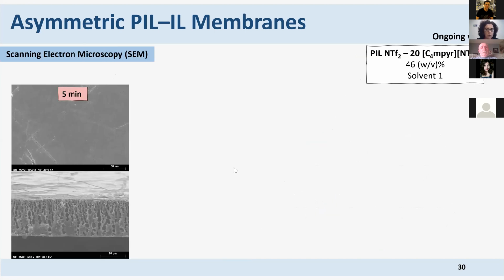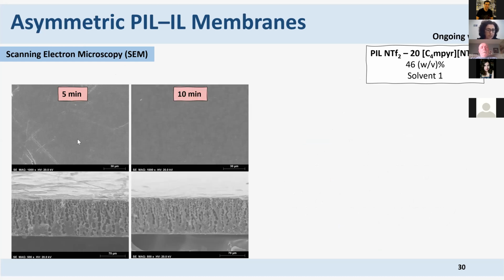So using solvent 1, we did 5 minutes of solvent casting, and then we just put our membrane inside of the coagulation bath that is water. We can see here that the top layer is dense, and we can see in this cut that we have finger-like morphology. This is after 10 minutes.